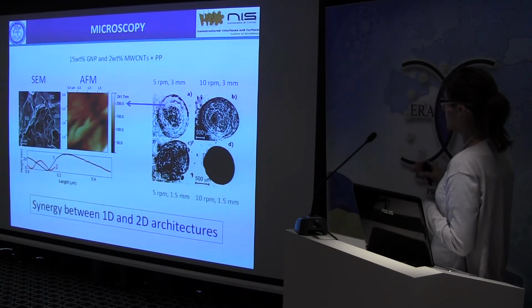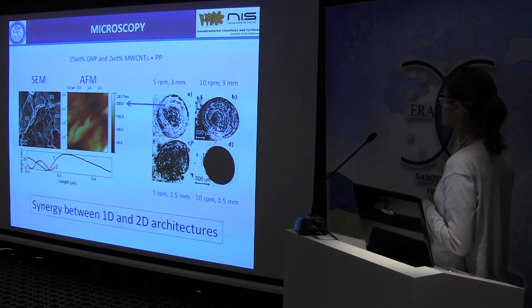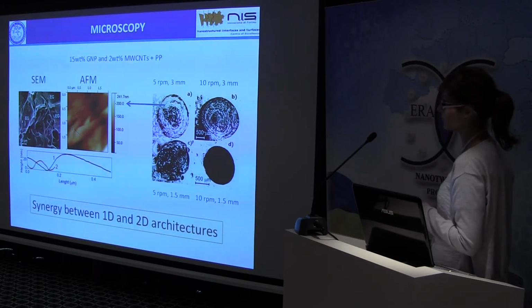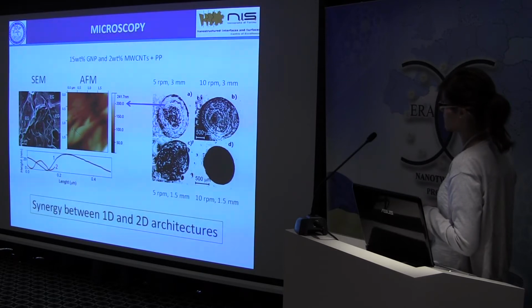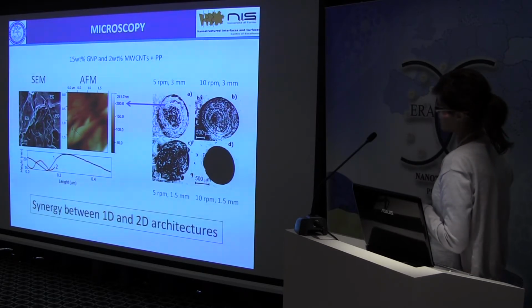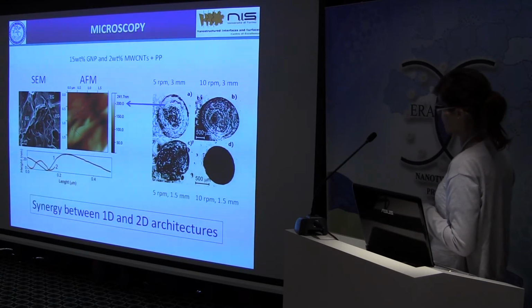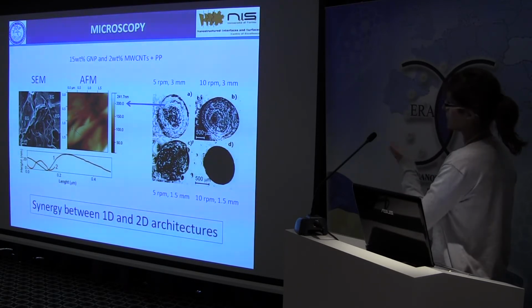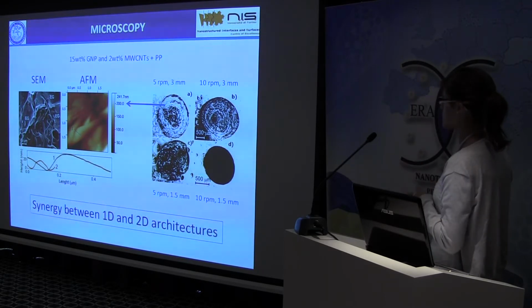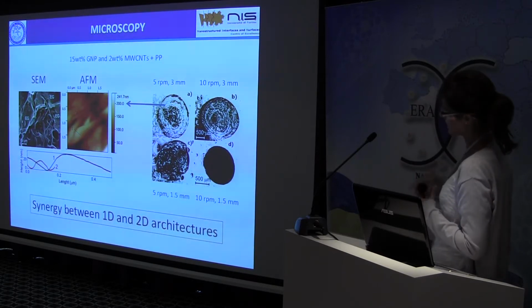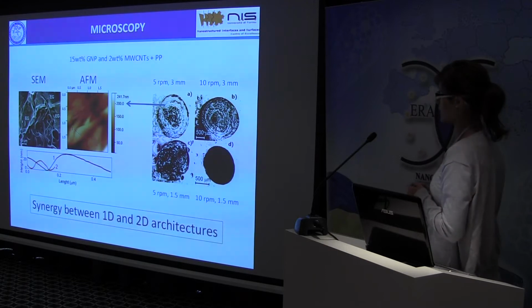And so we tried to see with this technique fibers which were obtained with different extrusion rates and with different diameters, and we discovered that the extrusion rate and the diameters affected the distribution of the conducting fillers within the matrix. The most conductive fiber is the one with a large bright area, where there's a large aggregation of conducting filler. Then this conducting area was analyzed by conventional SEM and AFM.